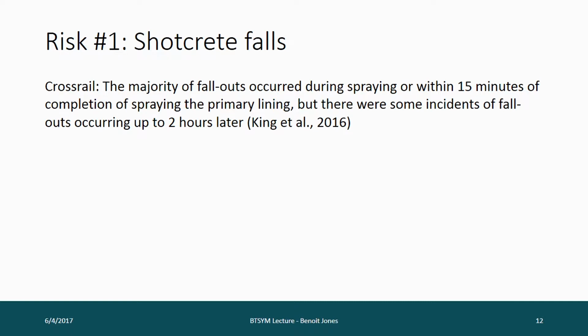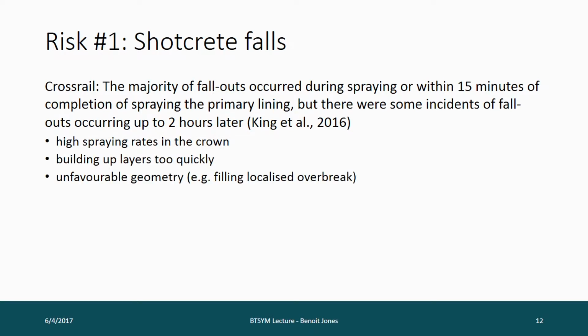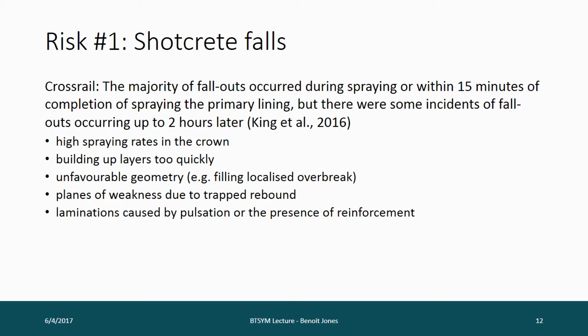So looking more in detail on Shotcrete falls, Mike King and others wrote a paper in 2016 about a study of all Shotcrete fallouts on Crossrail, and the majority occurred during spraying or within 15 minutes of completion of spraying, but there were some incidents of fallouts occurring up to 2 hours later, and they listed the main causes: high spraying rates in the crown, building up layers too quickly, unfavourable geometry, like filling localized overbreak, planes of weakness due to trapped rebound, laminations caused by pulsation, that's when there are differences in concrete flow due to the pump, or the presence of reinforcement.